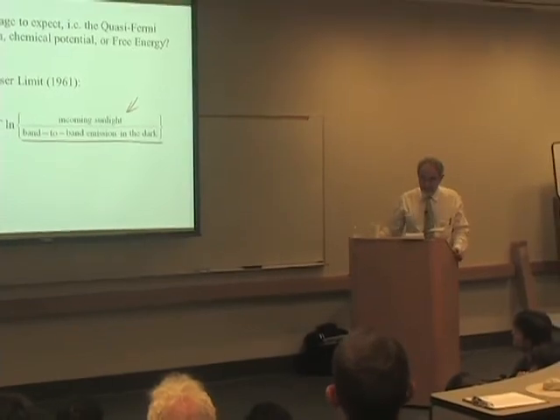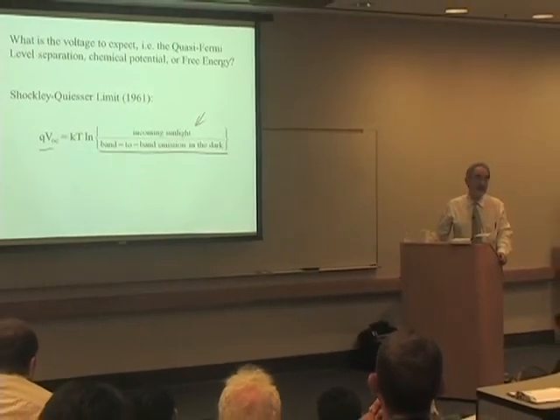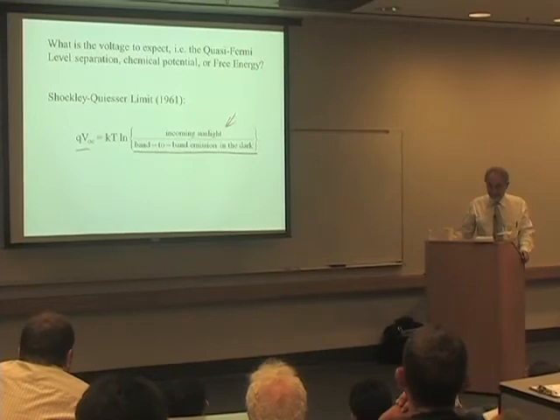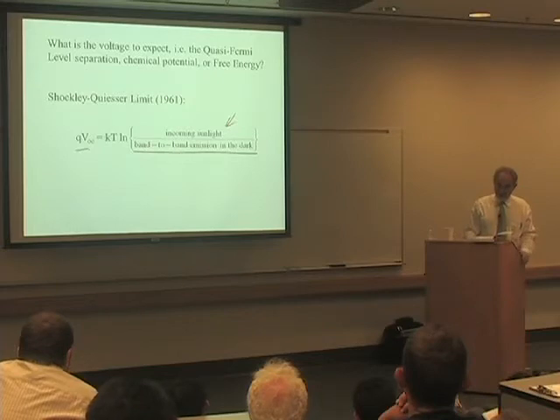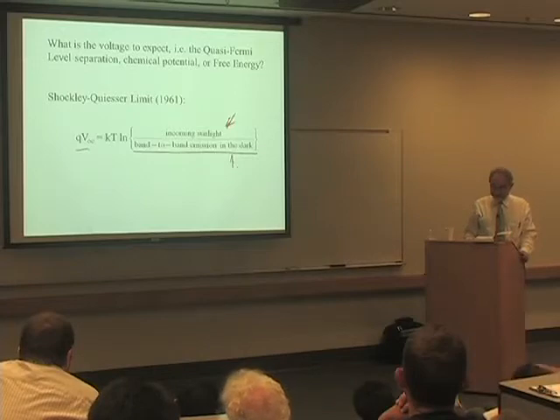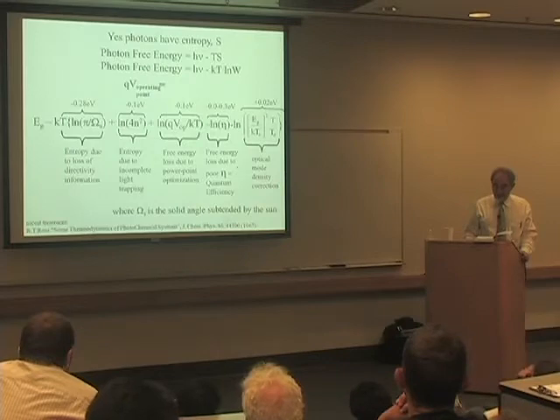So this was embraced by Shockley. Shockley figured all this stuff out, and this is another way of writing the same formula. It's the natural log of the incoming sunlight versus the internal emission in the semiconductor. So how can a dark, cold semiconductor emit? Yes, there's always a little tiny amount of light emission. Maybe it's one photon for every 10 seconds, but it's that ratio. It's like a ratio of probabilities. The sunlight versus the small amount of background light emission, that determines the open circuit voltage. So that's kind of nice, and it's beautiful, and it's elegant.